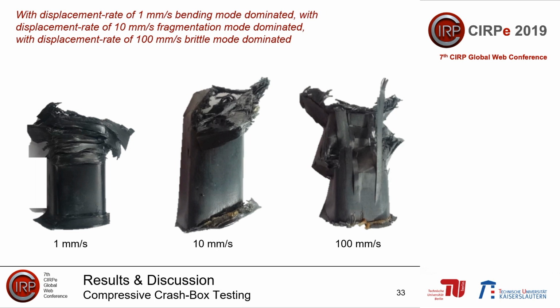And as we increase the displacement rate, what is happening is that the crushed length is decreasing, and as the crushed length decreases, each of those properties that we saw on the previous slide is effectively increased. So that's the explanation for the trends that we see.